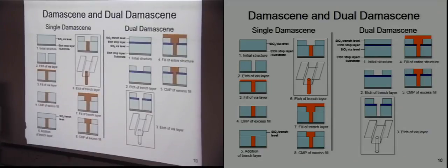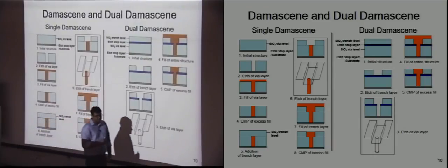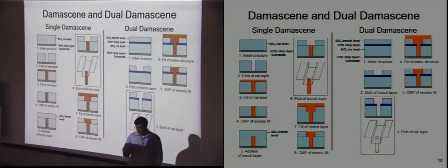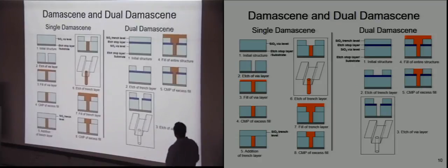Okay. So, by using 2 types of etch stop layers, we start off, we form the trench layer, then we strip off the silicon nitride, we pattern one more layer below it such that it is the via, and once both the trenches and the via are done, we fill it up with copper. Okay. And the copper is deposited through a process of electrodeposition, details of which Prof. Puisi will talk about in the future.